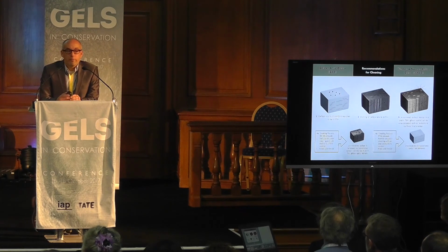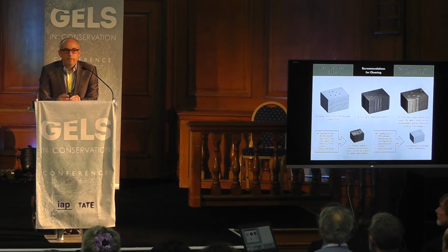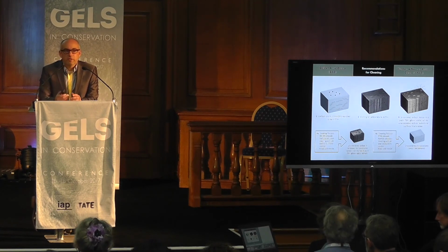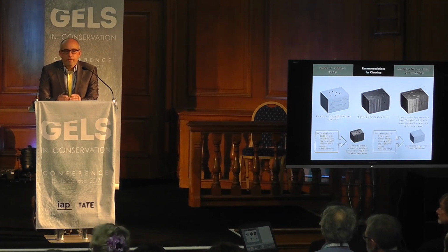And so what Richard and I would probably propose is that there are two types of soiling mechanisms going on in these two different paint bodies. Both contain surfactants. However, in one paint body, we're going to have the associated soils, such as the acrylics with the alkyl phenyl ethoxylates, and we're going to have to work a little bit harder at the surface of these paintings to get those cleaned. We're going to have to devise cleaning systems that include some degree of aromaticity. In the Winsor & Newton Artisan Colors, we're probably working with more dissociated soils because of the lack of that aromatic substituent, where they can be removed primarily from the surface, working with less invasive cleaning systems.